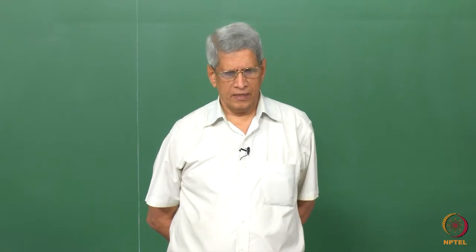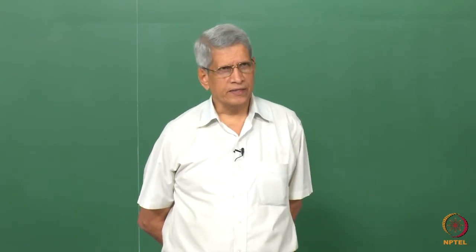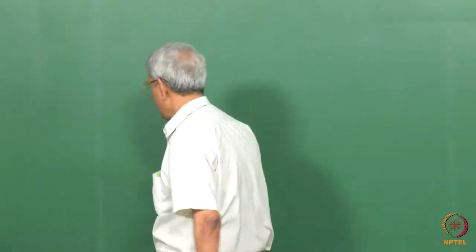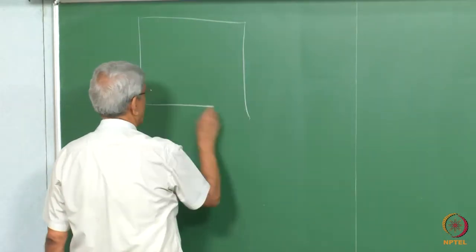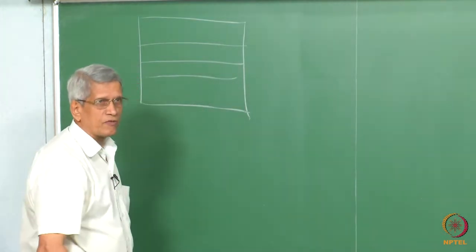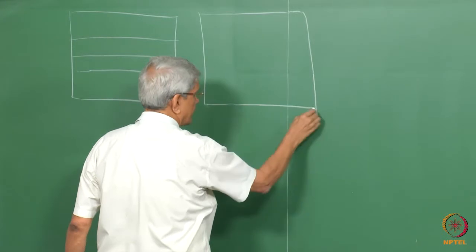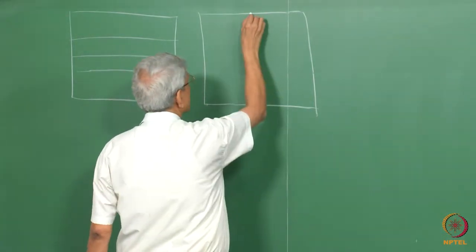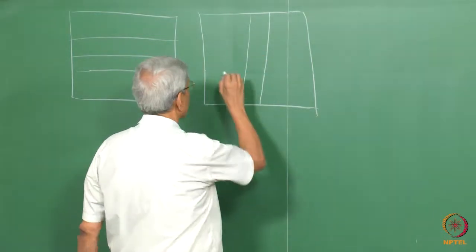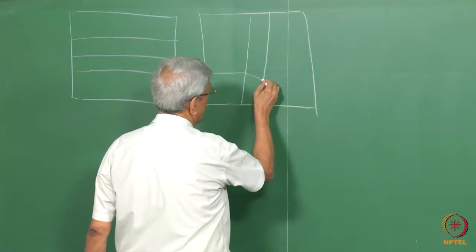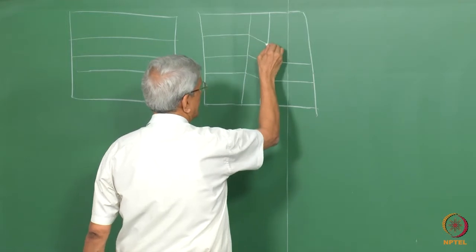what essentially happens is that if we take a well polished sample and put line scratch marks on the surface of the sample, and then do a heat treatment, then observe the sample after the heat treatment in even an optical microscope, we suddenly find that in that sample, the simplest case which we can consider is that there is one line which comes, and we find that this is the way these lines are getting deflected.